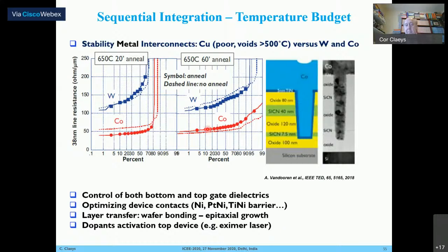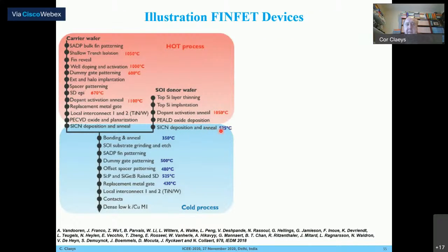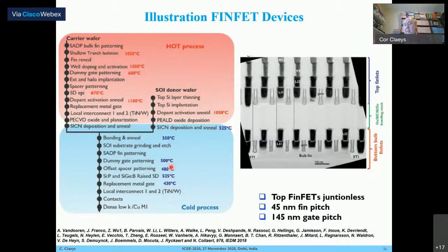That's a possibility. Another approach has been proposed by IMEC, where they are using standard silicon wafer processing on one wafer. On the second wafer, there's an SOI donor wafer. They already do the dopant implantation and annealing at high temperatures. Then you do a wafer bonding, and then they are fabricating the devices in the top layer, in which case they are using a cold process. That's an example where you got at the bottom bulk FinFET, and at the top you got junctionless FinFET. But there are different combinations possible, as already mentioned.